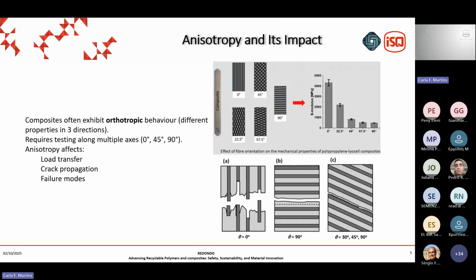Obviously, the anisotropy or the potential anisotropy also affects, for instance, properties like the load transfer between fibers and the matrix, which in turn affects the crack propagation or defect propagation and potential failure modes, as is depicted here at the bottom, in which we can have failures of the fibers themselves together with the matrix, or in other directions other than the longitudinal direction, the 0 degrees direction, we might shift into cohesive failures in the matrix itself or adhesive failures between fibers and that matrix. Fibers or other reinforcement media that is used.